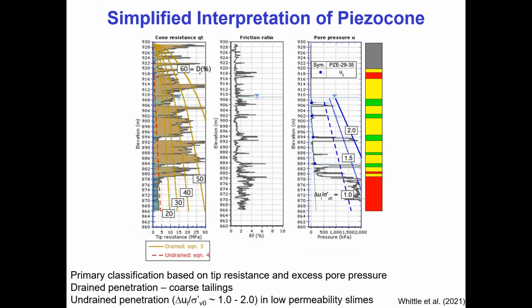The red line is essentially saying we know the undrained strength ratio, we know the cone factor, and this is our fit. And you'll see that we're correctly getting the right order of the cone factor. The fact that the cone factor is lower than we might expect, having a lower NK, may suggest something else that no one measured, which is the clay here may still be consolidated, maybe under consolidated.